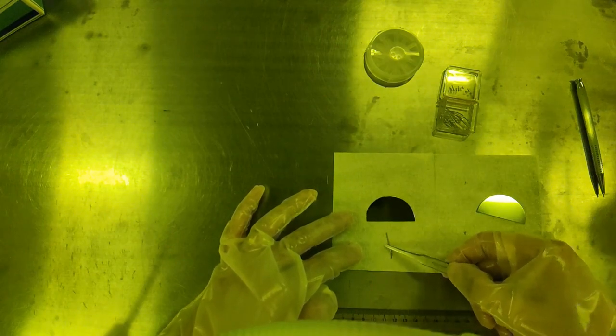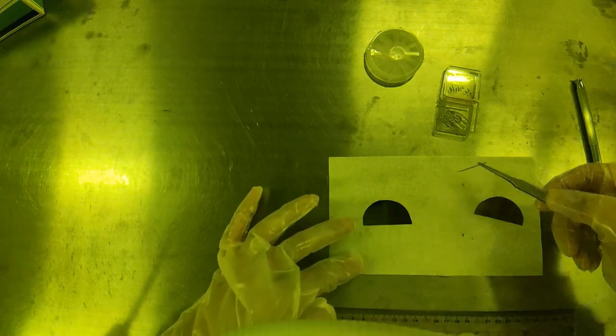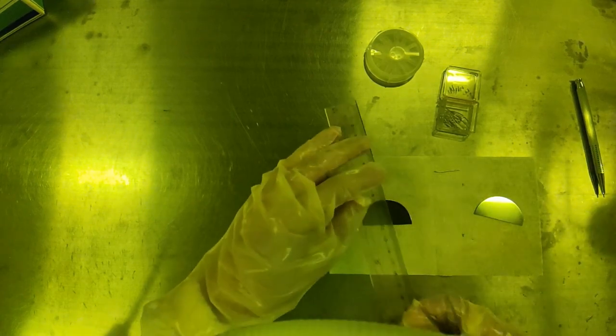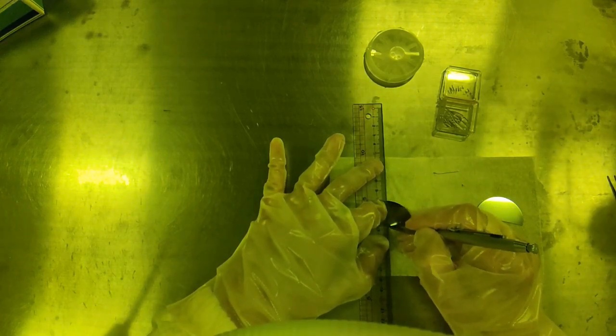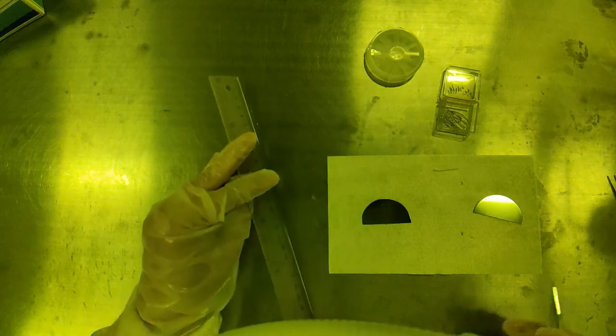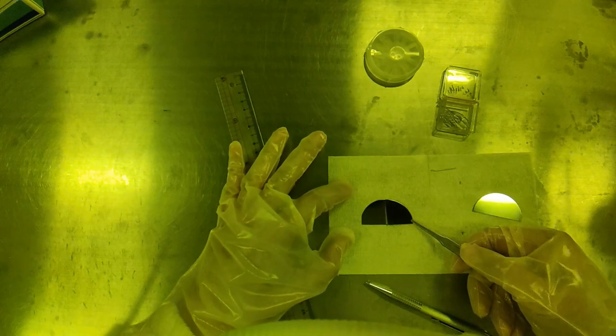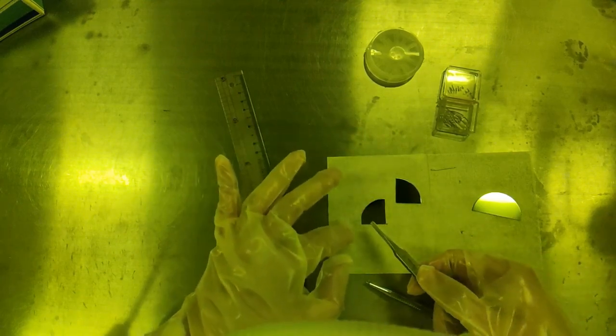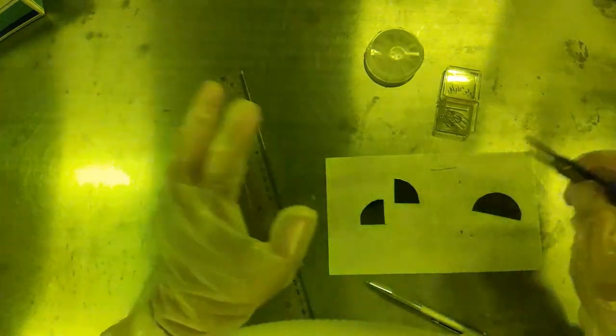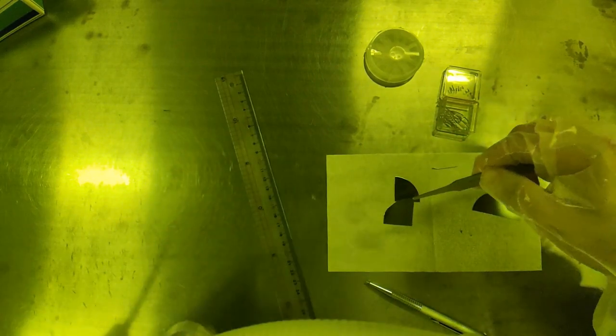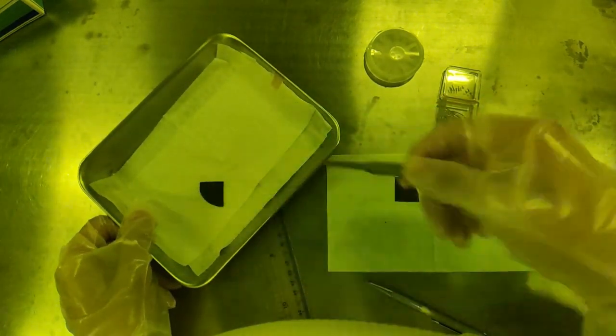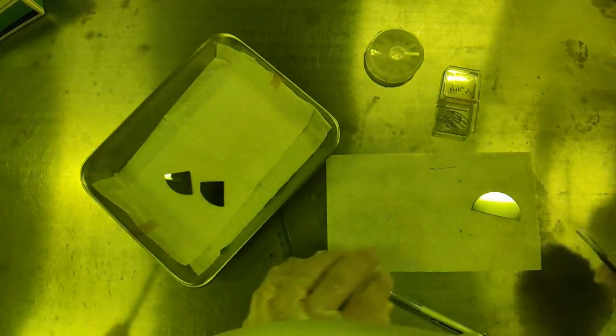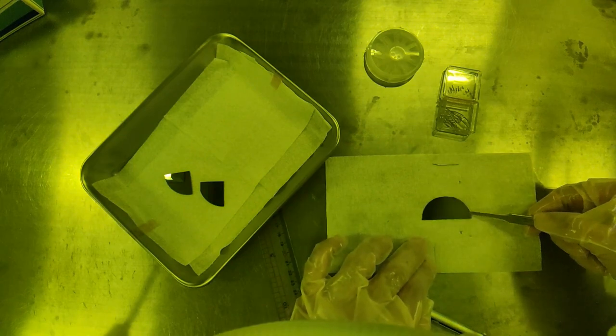See? Now you can see the cut. Nice. So, next step is to smash it a bit, so the crack which was on the surface will propagate through the whole wafer. The second trick is to use the clip. Paper clip. And there are a few broken ones, but I just like to use a piece of wire from the paper clip. And to put it over, like this. The main trick is that you really don't need a lot of force, so just like this maybe. But sometimes it just doesn't break. Oh, here we go. You can hear the crack. And now it's clearly cut. I want to clip it in four. So, here and here. I will just do it in a fast manner. Only possible with silicon, by the way. This kind of side pressure cleaving. See? If you try to do it with silicon carbide or gallium nitride or sapphire even, it will just shatter in a thousand pieces.